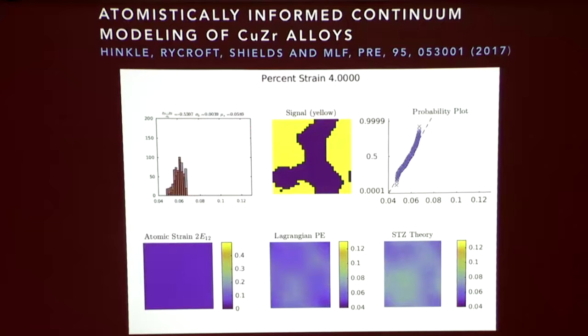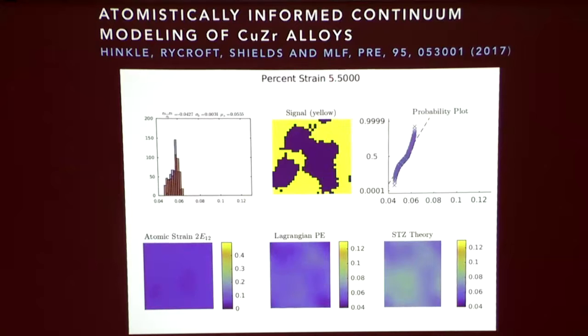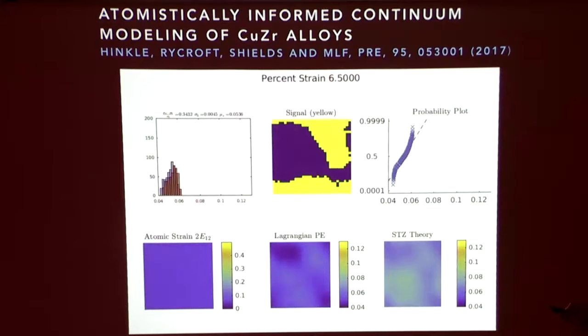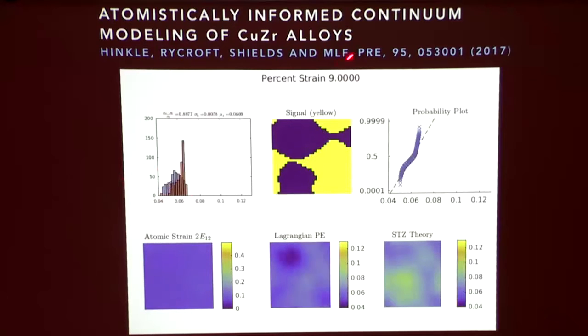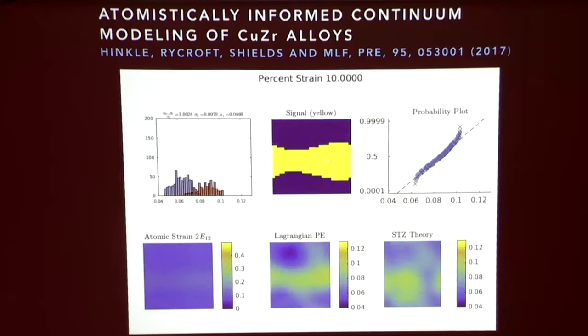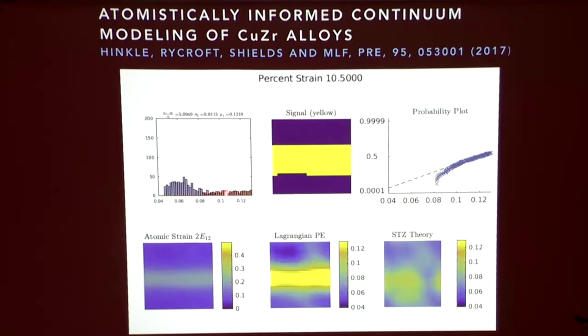So you see here it's just fluctuating around. We're at 4.5% strain. It's more or less behaving elastically. The potential energies are all sort of indistinguishable from each other in the two regions. Then around 9% strain, you'll see localization develops. The potential energies in the two regions are quite distinct.